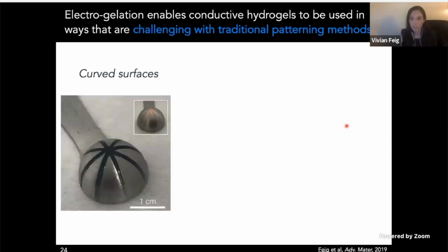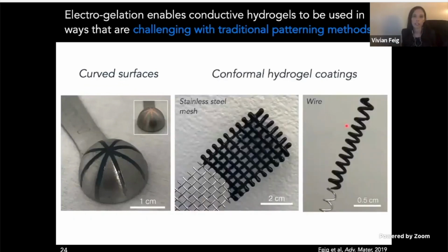And finally, since electrogelation is a surface-based method, not only can we make these high resolution features on planar surfaces, but we can also readily pattern onto curved substrates. Or if we use electroplating instead of evaporation, we can also really easily generate these conformal hydrogel coatings while maintaining the 3D structure of whatever we're trying to coat. And so this just expands the options overall for how we can integrate these conductive materials into devices that might have different or unconventional geometries.